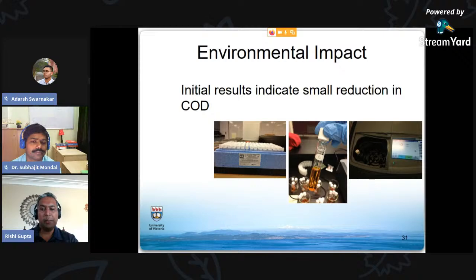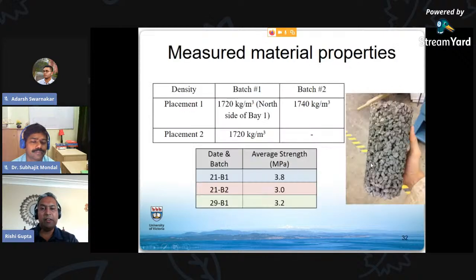We did some COD measurements on the project, and we did density measurements. You'll see that the compressive strength of these samples were rather low. The product that we were working with, we were expecting more like 10 MPa, but I attribute this issue to the fact that there was at the time no standard that spoke about how this should be cast. So, what level of compaction? How do you actually make this? Was an issue. But I think the low compressive strength is attributed to the fact that there was no standard explaining how cylinders should be made for porous concrete.